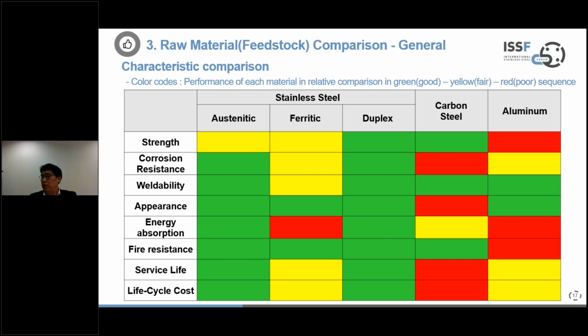For example, strength. We know that aluminum is the weakest. Corrosion resistance, carbon steel, yes, it's very vulnerable to corrosion. Weldability, more or less the same. Appearance, this actually goes in part with corrosion resistance. Carbon steel has the poorest numbers on it. Energy absorption, ferritic, stainless steel, and aluminum, not so good. Fire resistance, aluminum has the lowest mark because aluminum's melting point is the lowest. Service life, this also goes hand in hand with corrosion resistance. And finally, the life cycle cost also shows a similar picture to service life. So you can see on the characteristic comparison, in most factors, stainless steel holds the upper hand.